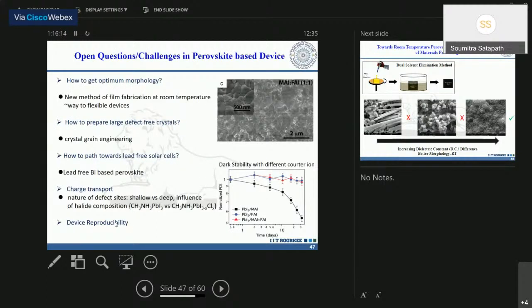But scientists have also come across ways in which we can make reproducible devices by minimizing the aggregation. But one question which is still unsolved is the stability. If I make a perovskite solar cell giving me 25% efficiency, that is well and good. But what if the solar cell just dies in 10 seconds or 10 minutes, let's say? That will be of no use. Usually the solar cells are made in a very controlled environment, in a controlled chamber called a glove box, where you can control the oxygen level and the humidity level, right? But once you try to make them outside, they degrade quickly.